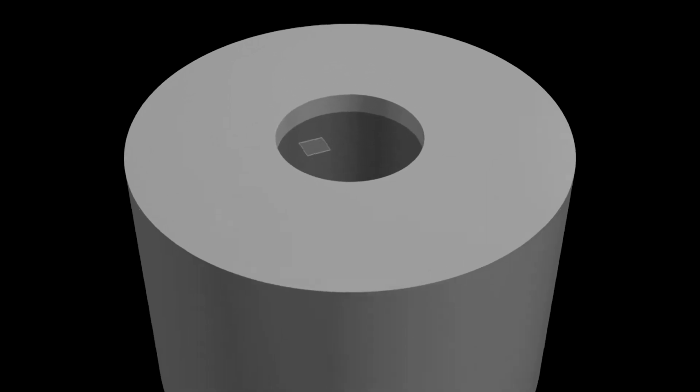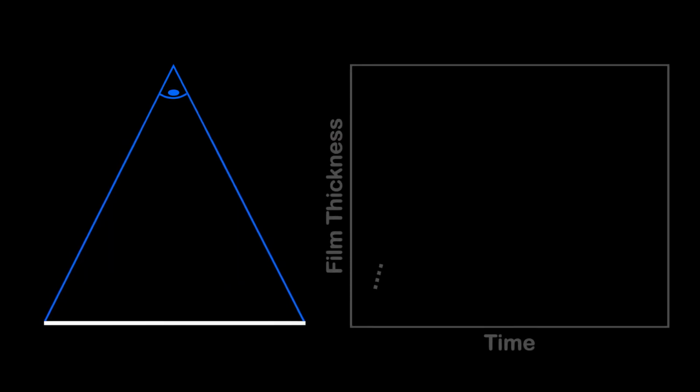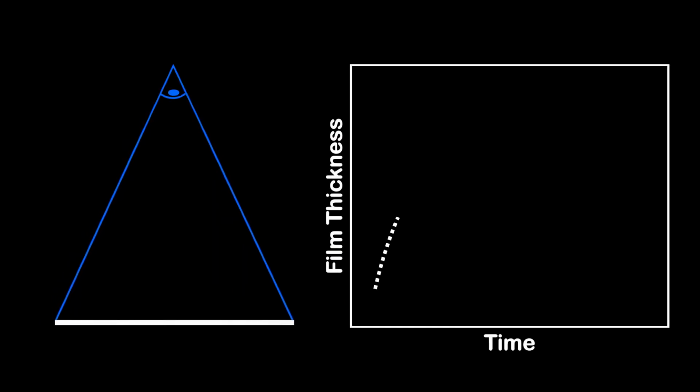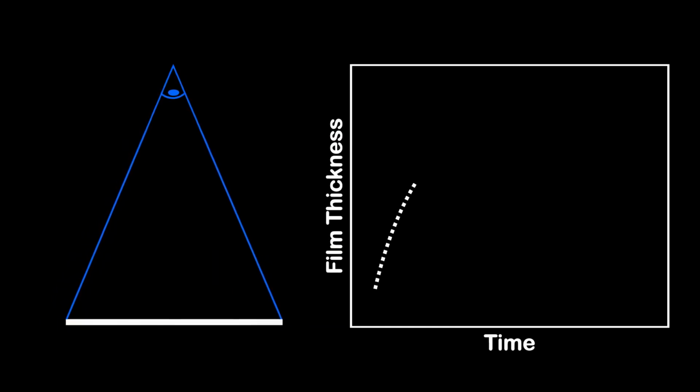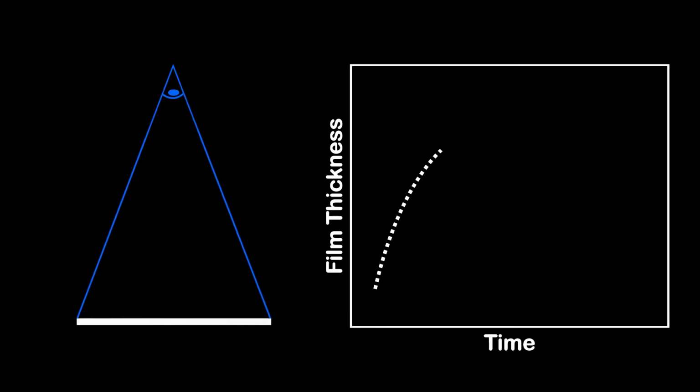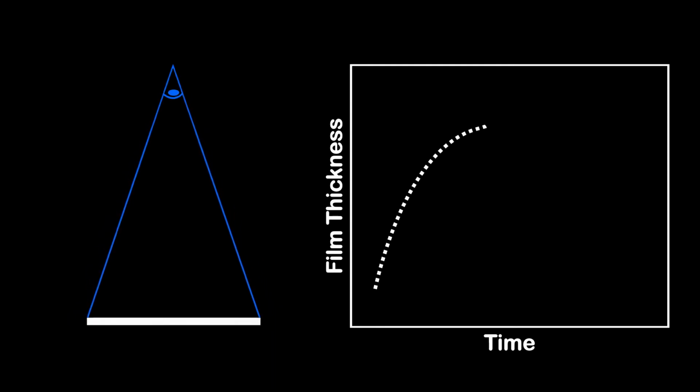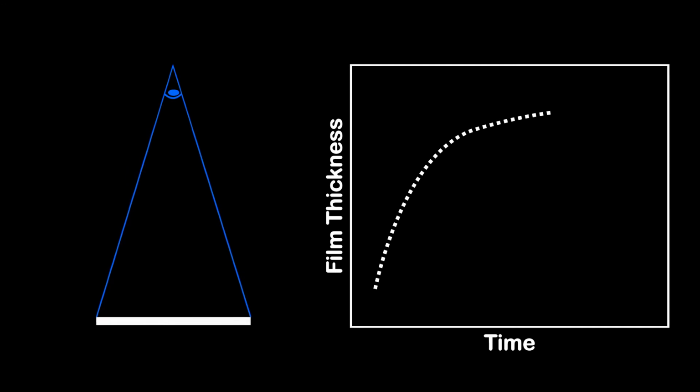The basic concept of liquid de-wetting is this. A heated glycerol bath supports a thin polymer film, and the relative surface tensions between the materials induce stress in the film, causing it to shrink, or de-wet from the glycerol. The film's thickness can then be calculated using the change in surface area over time. From these values, standard mechanical properties such as modulus and compliance can be extracted.